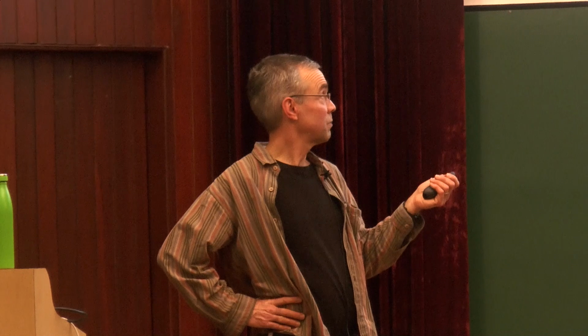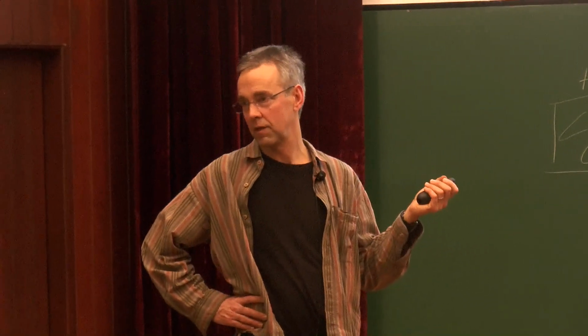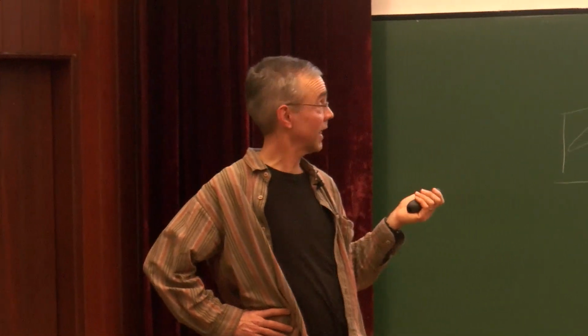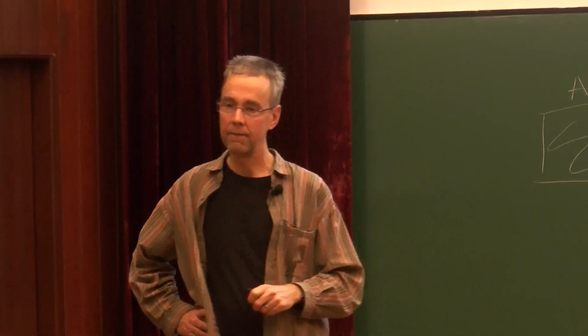From an experimental perspective, what would I look for in an experiment to see this? What would be the rheological signature that I can measure? The yield rate should be linked to dissipation, so in principle you can measure dissipation per cycle. We have not actually checked within the model, but that should be a reasonable proxy. Can you measure the number of events? Yes, if you can measure the number of events, even better, because that's directly this. But of course, that requires more analysis. If you only have macroscopic stress and strain, then the dissipation should give you a reasonable proxy, I think.